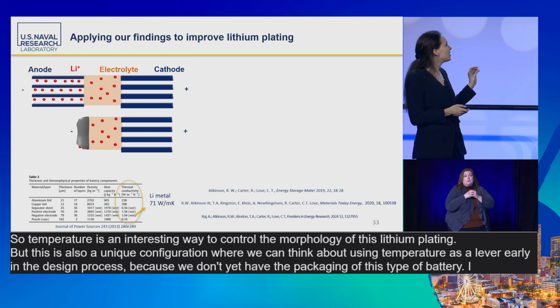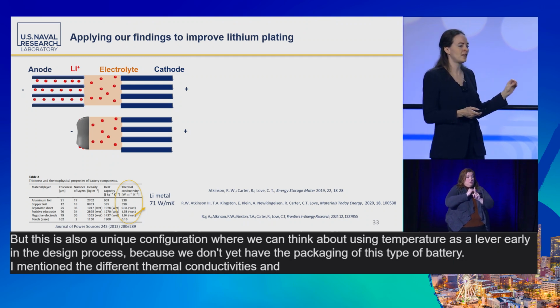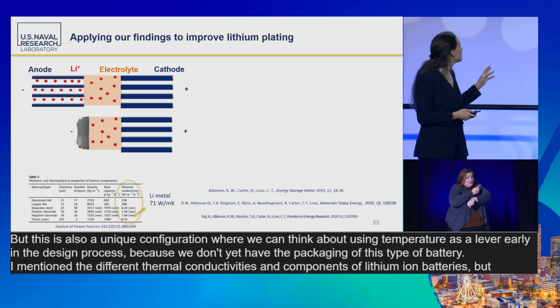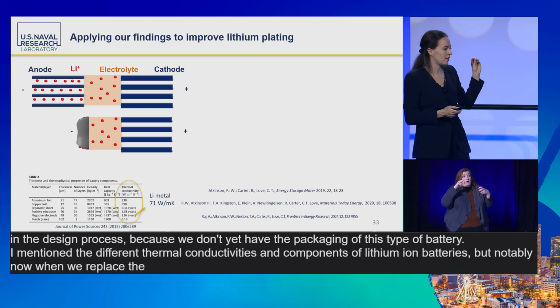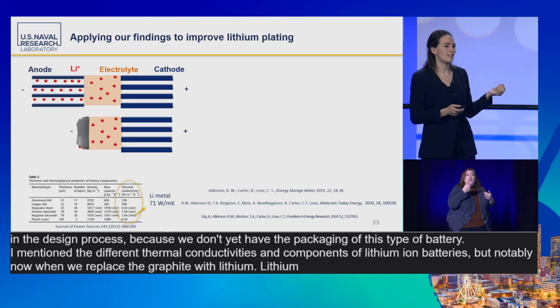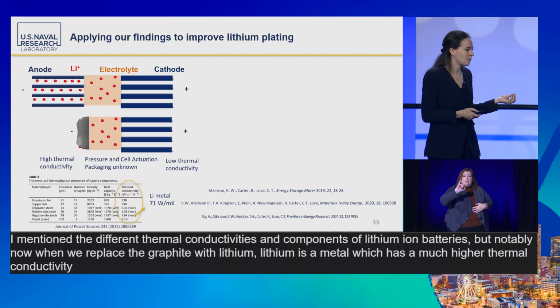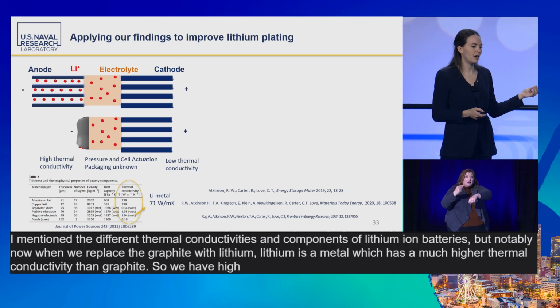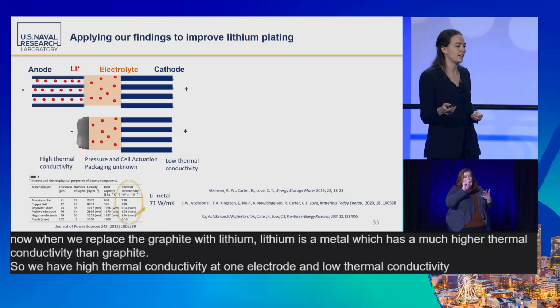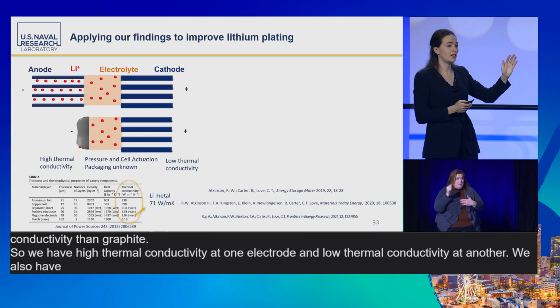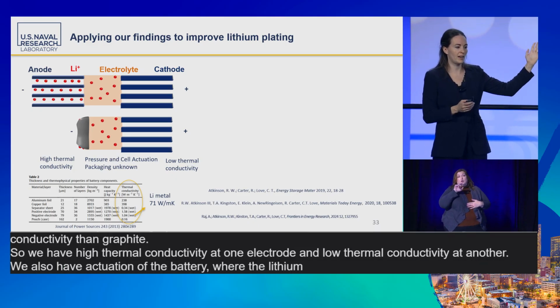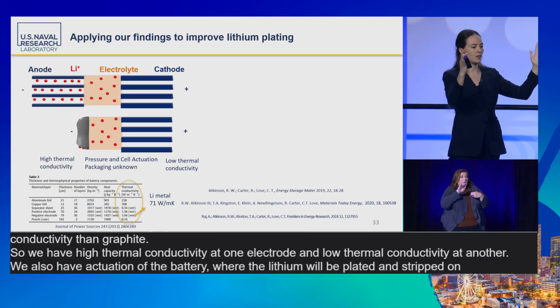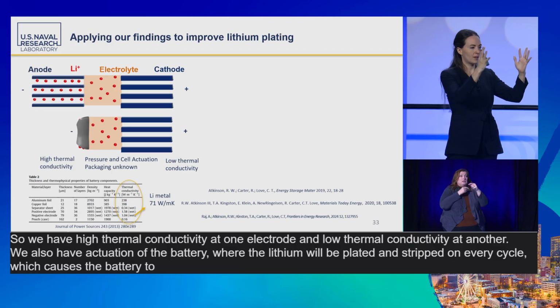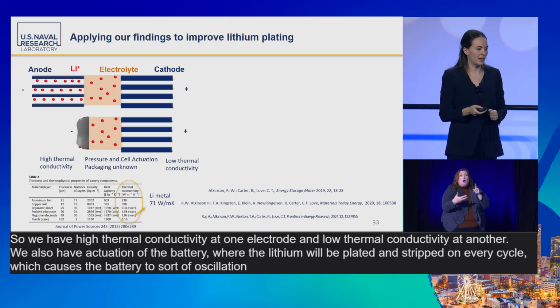I mentioned the different thermal conductivities of components of lithium-ion batteries, but notably now when we replace the graphite with lithium, lithium is a metal which has a much higher thermal conductivity than graphite. So we have high thermal conductivity at one electrode and low thermal conductivity at another. We also have actuation of the battery, where the lithium will be plated and stripped on every cycle, which causes the battery to sort of oscillate upon cycling.